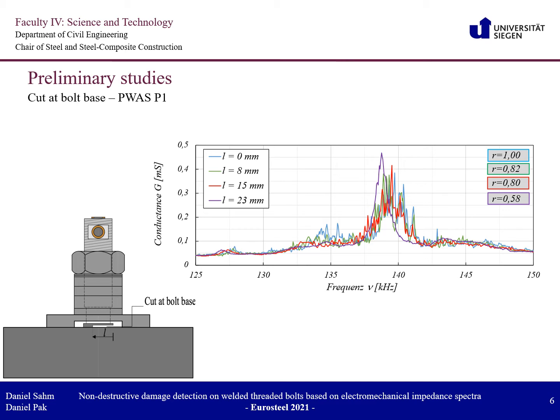For the preliminary tests cut at bolt base, the test specimen was cut at the weld bead with a metal saw. You can see the cut right here. The depth of the cut was increased in steps of 1 mm after each measuring cycle. In the diagram you can see the graphs of the measurement series undamaged, 8 mm, 15 mm and 23 mm. A 23 mm cut depth was only possible because the weld seam diameter was approximately 23.5 mm.